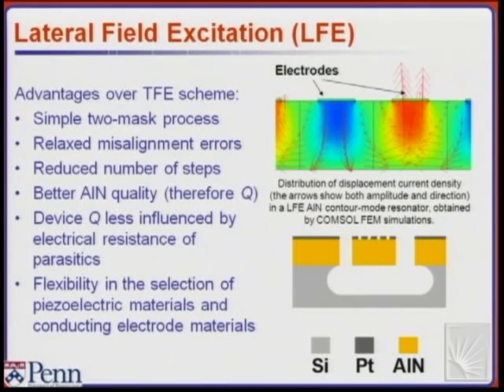So we've also made different types of devices in which we basically do not put a bottom electrode, but we just use the top electrode to route the electric field. This is an interesting solution because it really simplifies the process. My students love it because with 2 masks they can make a device essentially, right? So it's very easy, not much processing involved, and you can really get good devices. Actually, we've done it at high frequency. It's very easy. You don't have alignment issues or anything.